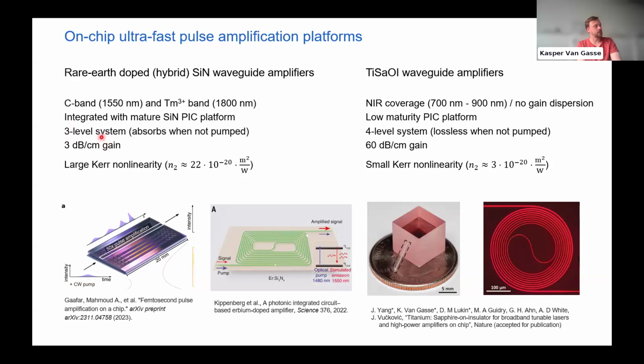But the gain per unit length is also pretty low. So you need a very long amplifier to get significant amplification. And that also means that you need to take a lot of dispersion engineering into account. And on top of that, silicon nitride has a very strong Kerr nonlinearity. And that means that you can have a lot of nonlinear deformation of your pulse.